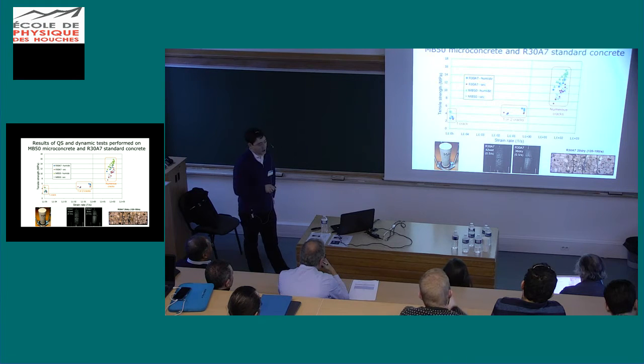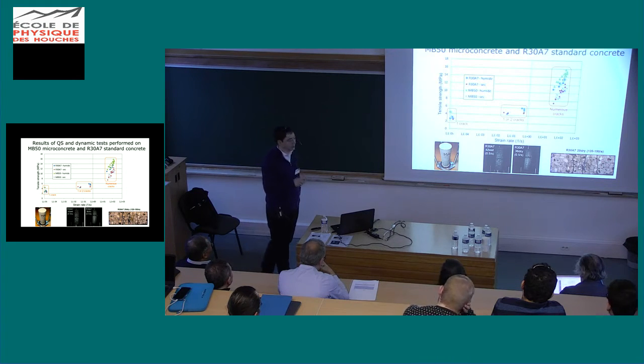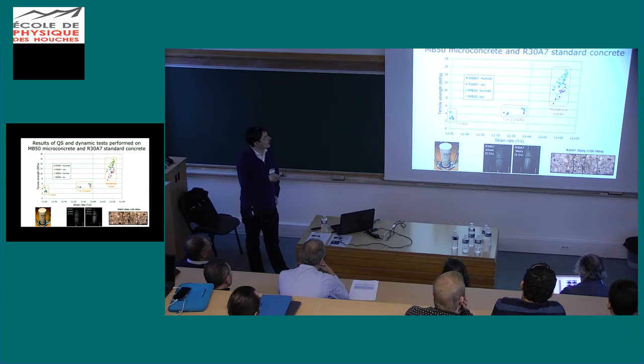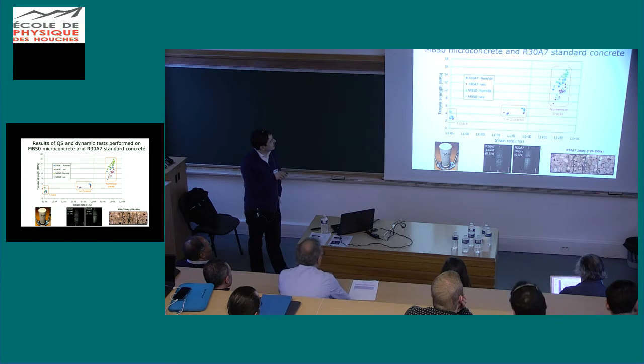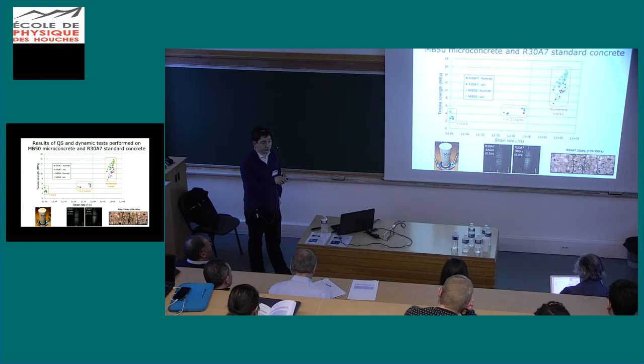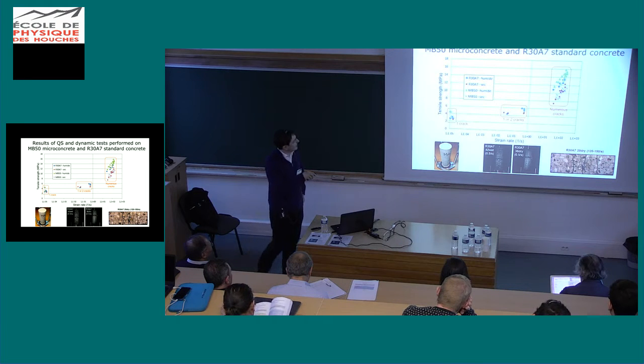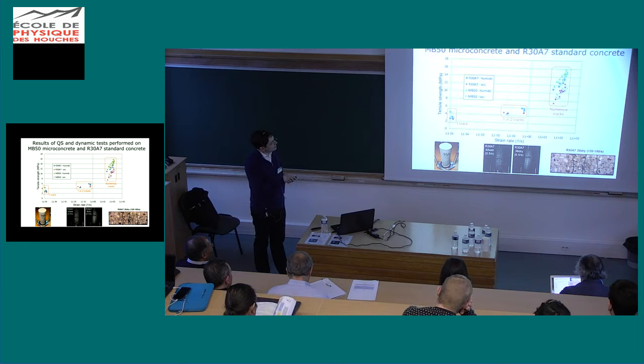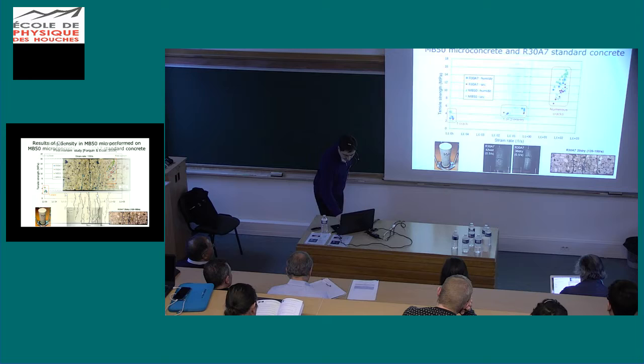And what was also very interesting to see is the influence of humidity. So, for instance, you can see here a wet concrete, the blue diamond. The green triangle corresponds to wet microconcrete. So the same strength is observed, so there seems to be no big influence of aggregate size. Whereas much lower strength can be observed with dry concrete or dry microconcrete. Okay, so this is an important point.